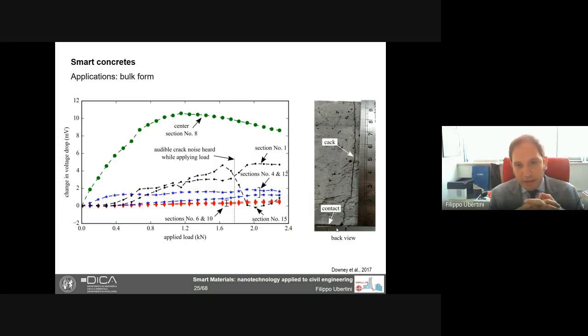Then what is also nice to notice is that with black lines, blue lines, and red lines, we have sections that are located at symmetric positions with respect to the midspan. And more or less, they give consistent results because the problem is symmetric, apart from, of course, the random distribution of the electrical property of the material. But from the mechanical point of view, it's a symmetric problem. So we should see the same result on both sides, which actually is the case.